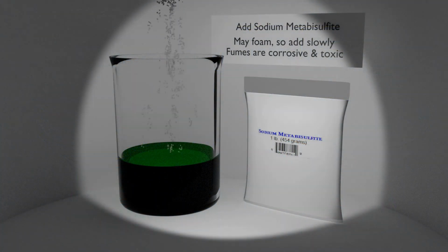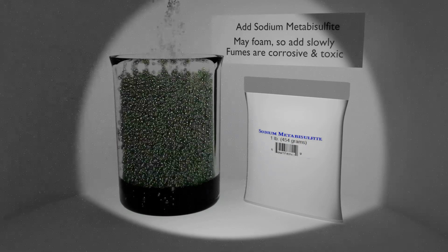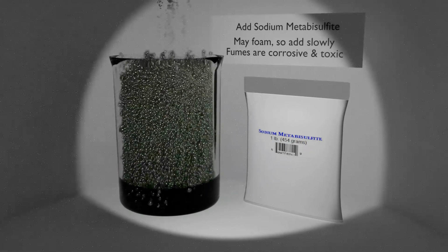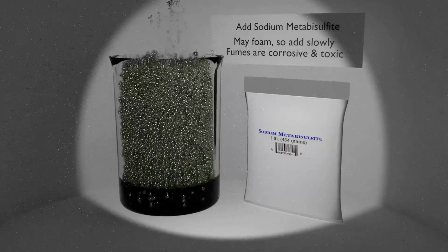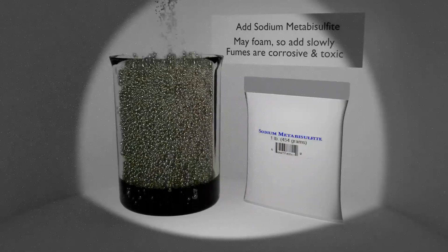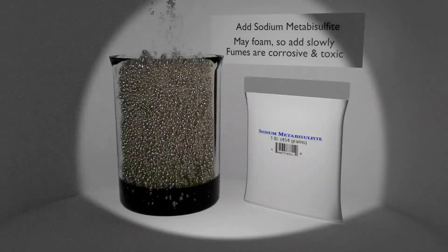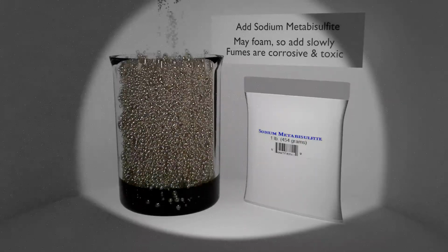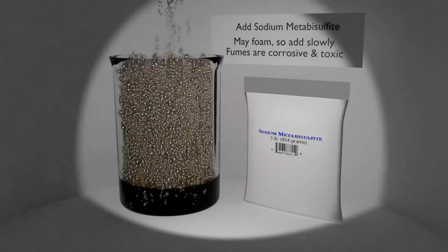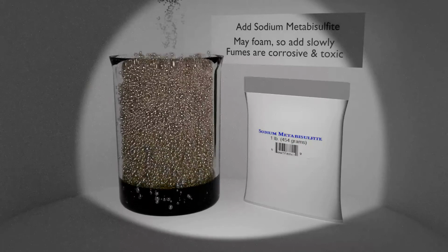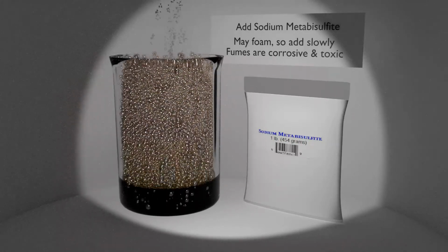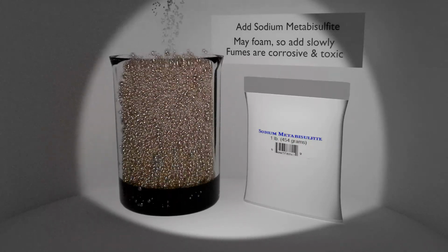Precipitation using sodium metabisulfite. Do this inside of a bucket. Sodium metabisulfite has a tendency to foam out of its container. So add it slowly, and do not heat the solution. Stay well away from the fumes. Typical precipitation time, at room temperature, is about 30 to 60 minutes.